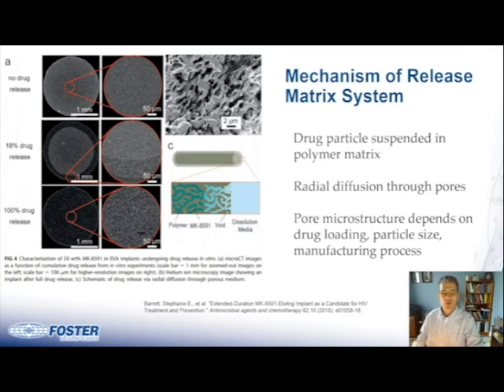These images show the drug release through percolation or particle-particle contact. So you can see there's no drug release here. You can see all of the particles in the image, and then at 18% drug release, you can see that it's releasing from the outside in towards the core, and at 100% drug release, most of the drug has been depleted. These micrographs really show the voids that are created as the drug is released over time.